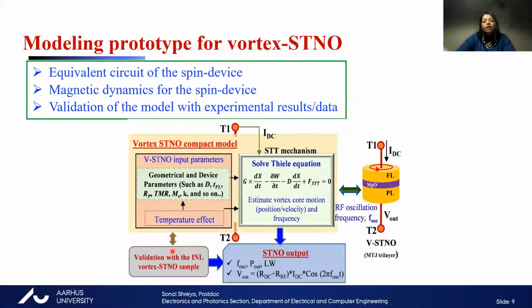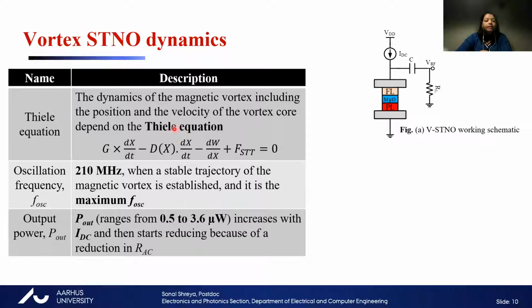Then it will give us output, and of course the model should be validated with the experimental results, that is, when we measure the sample, it gives us output in the form of the oscillation frequency. We can measure that frequency because it is an electrical module, so we measure it in the form of voltage, and then we can use it for further applications. As I said, the dynamics of the vortex core include this Thiele equation, with which we can find the position and velocity of the vortex core, and it also gives us the frequency of oscillation. For the device that we measured and modeled, the oscillation frequency we can attain is up to 210 megahertz, and the output power.